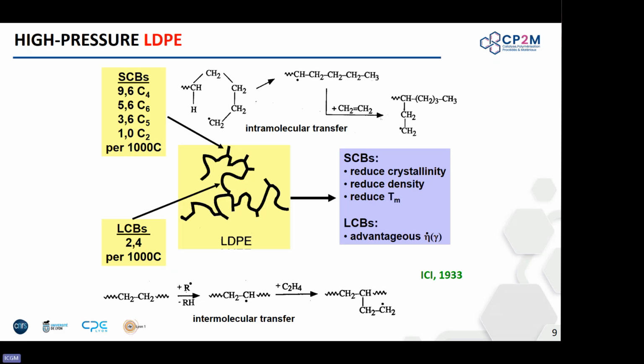The viscosity that the long chain branching gives you in the melt is so important, because it allows you to do, for instance, blowing type processes. If you don't have this melt strength, you will not be able to do that. So people claiming that with some LLDPE, you can match the properties of LDPE, it's not technically correct. This long chain branching is particularly important, okay?